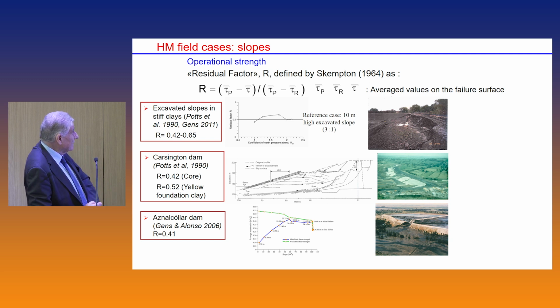Anyway, if we take this residual factor, which was defined by Skempton, in terms of averages, where are we in this back calculated strength between peak and residual? On average, obviously, that's the only thing you can do. We find that in the slopes it is between 0.4 and 0.6. In Carsington Dam, a very important case history because it cleared up a lot of misunderstandings about progressive failure, it's between 0.4 and 0.5. The Aznalcóllar Dam, a tailings dam that fell through a foundation failure, we found around 0.4. So it seems to be clustered between 0.4 and 0.5.